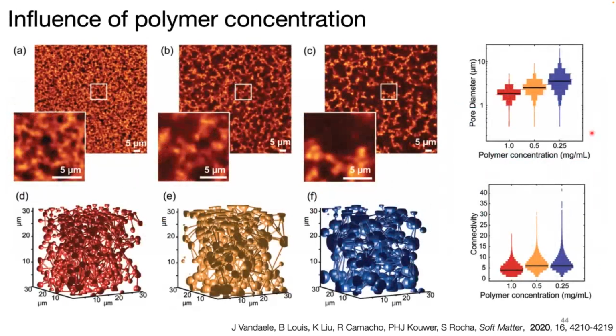And then we did that for different concentrations, and we see nothing very spectacular there: once you reduce the concentration, so you go from 1 milligram per ml to 0.5 to 0.25 milligrams per ml, the pore size increases. But even with this very low concentration, with this huge pore size, the material is still a gel, and it can be used to grow cells, but I haven't put any of that data here.